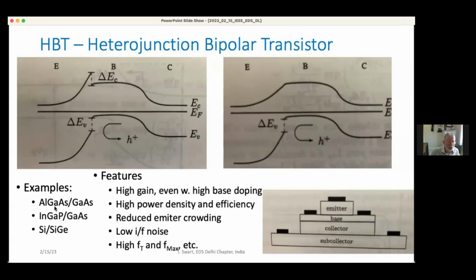So there are examples of AlGaAs on GaAs, InGaP on GaAs, silicon on silicon germanium. They all result in HBTs with high gain, even with a high base doping, which is important to reduce base resistance and emitter crowding. They also provide high power density and efficiency, and with low 1/f noise, characteristic of bipolar, and high fT and fmax. So those are characteristics of HBTs.